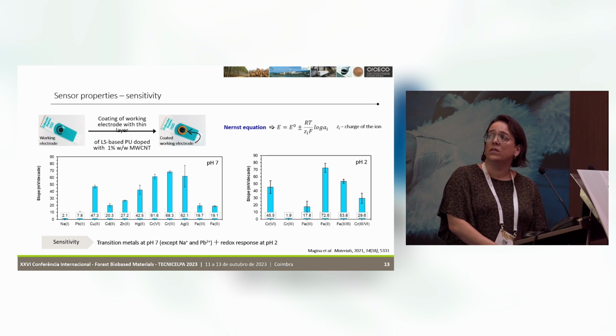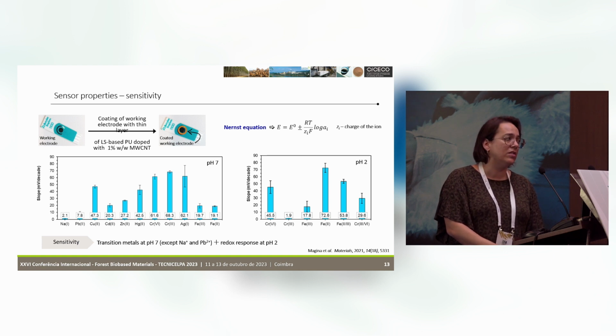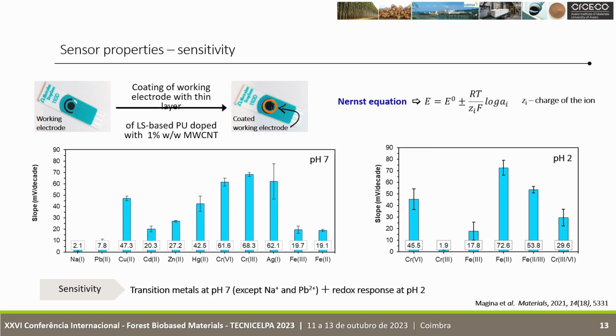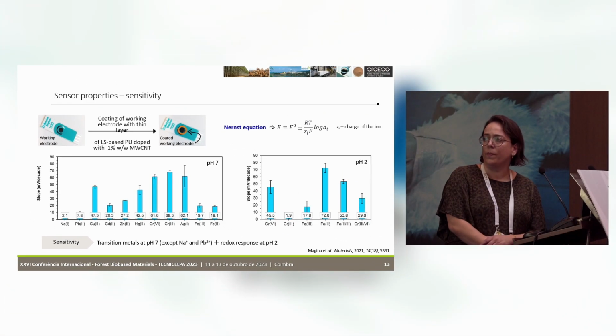So we prepared the sensors and measured the sensitivity to different transition metals. As you can see, at pH 7 this sensor is highly sensitive to several transition metals except for sodium and lead, and at pH 2 it exhibits some sensitivity but also redox response to two ion pairs, iron and chromium.